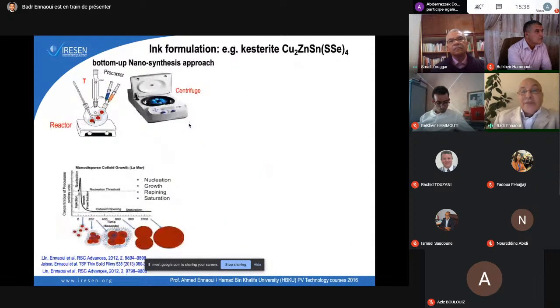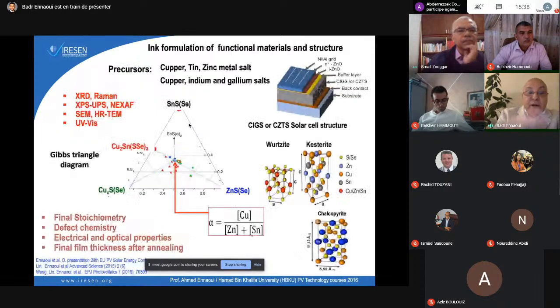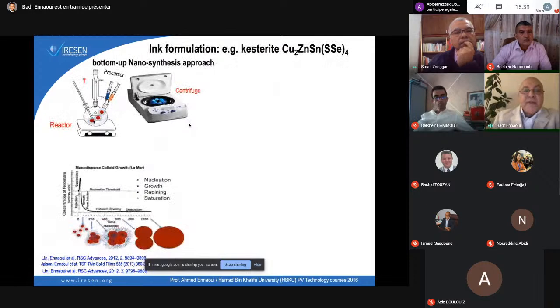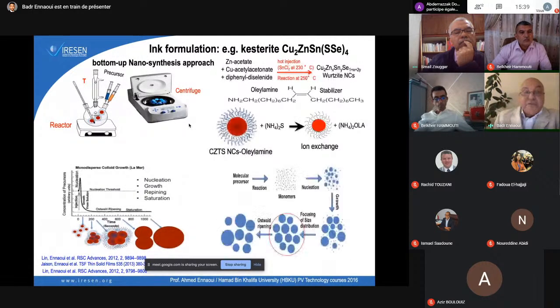So when we start, we work with a method that the chemists know very well, which is called hot injection, where you can have precursors and you can inject one or two precursors, like I showed you here before. You have, for example, zinc sulfide in your pot, and then you inject copper sulfide, or you have tin sulfide, copper sulfide, you inject zinc sulfide, etc. It depends. And then there are a lot of things to do in this process.